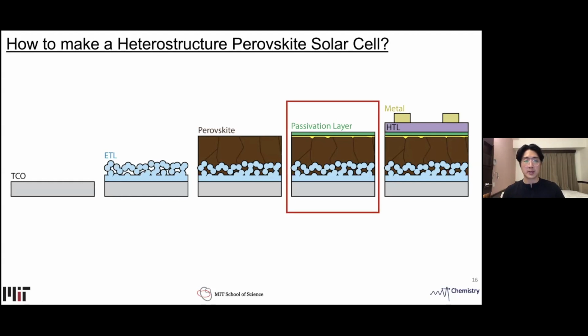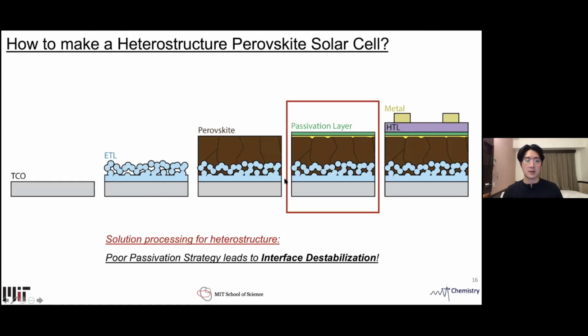However, with the fabrication being done in a solution processing manner, a poor fabrication protocol could lead to formation of unwanted byproducts, shown as this thin yellow layer. We in fact learned that a poor passivation strategy does lead to interface destabilization, which undermines the benefit you get from passivation.